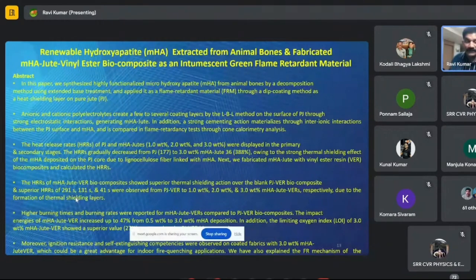So we studied here 1 weight percent, 2 weight percent, and 3 weight percent of MHA deposited on jute, including with VERs, which is due to the formation of thermal shielding on the surfaces. Those are the important factors here to understand the technology. Higher burning times and lower burning rates were reported through this material and this composite, and the limiting oxygen index was also improved using 3 weight percent MHA jute VER composite.